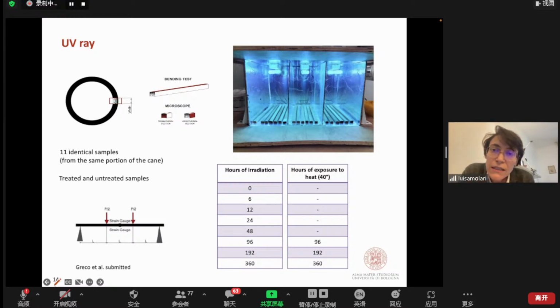What we did also, because when the samples were under the UV irradiation there was a temperature of around 40 degrees, is that we put some samples from the same portion of the culm, so more or less identical, in an oven at a constant 40 degrees for the same duration as the irradiation, to see if something changes. So, in some sense, to separate the two effects, the effect of the temperature and the effect of the UV irradiation. And what we saw is this.